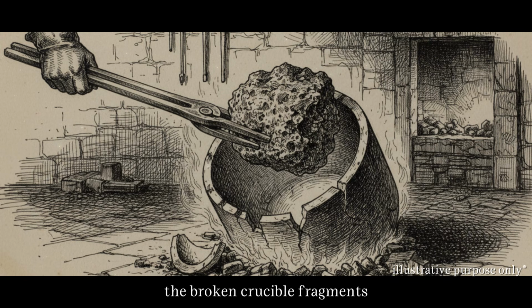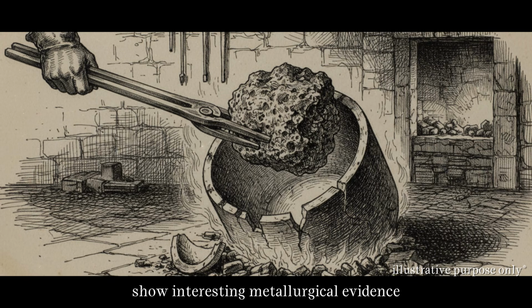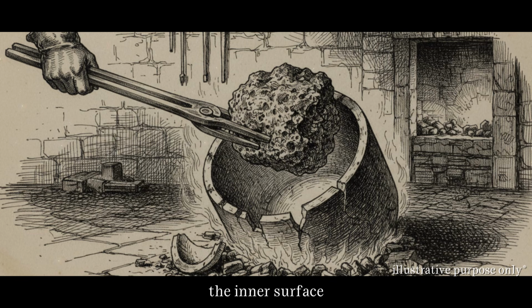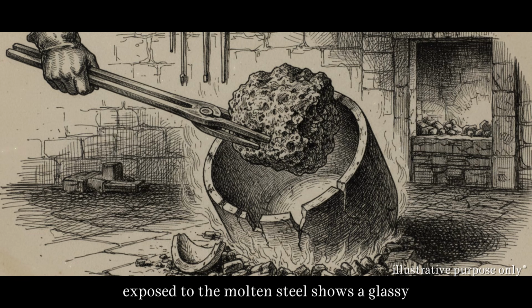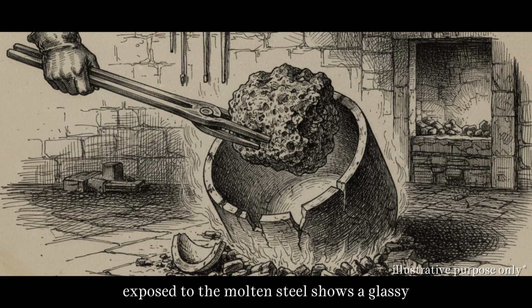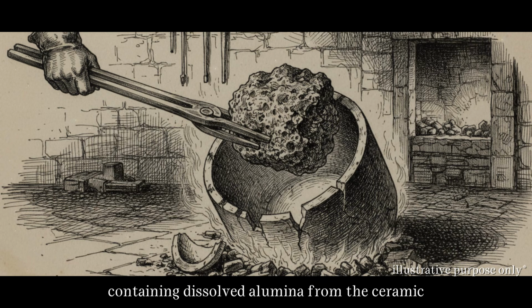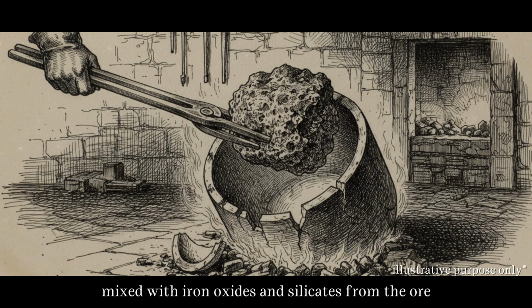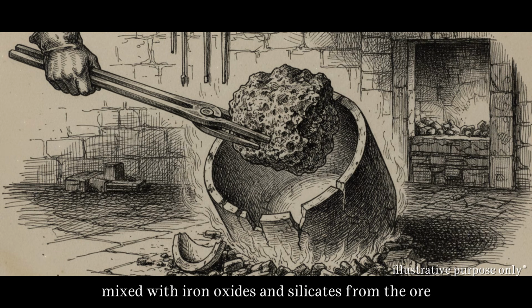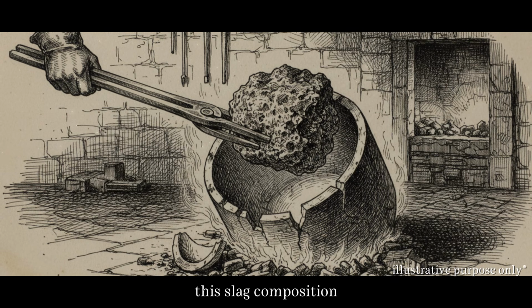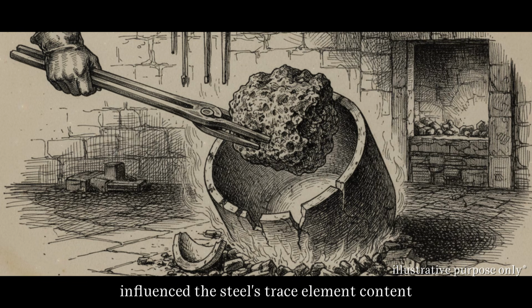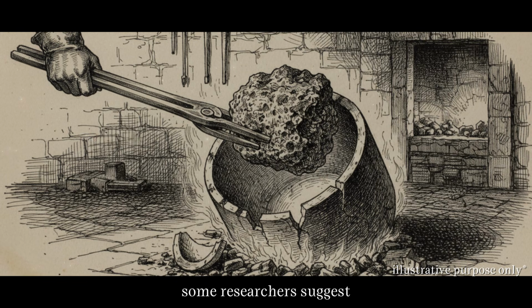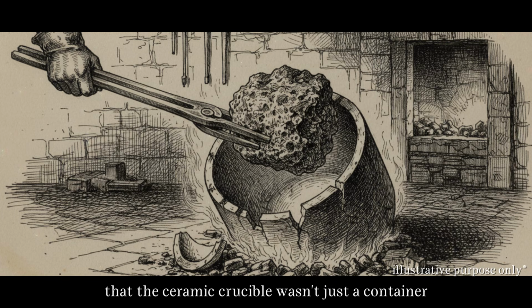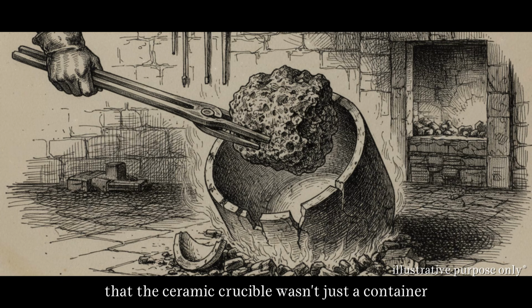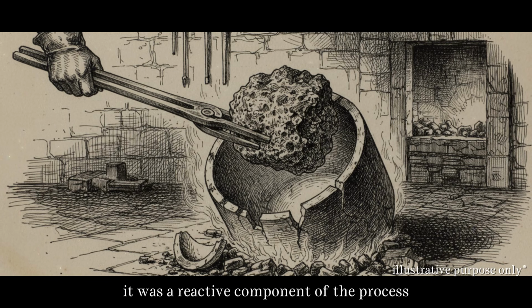The broken crucible fragments show interesting metallurgical evidence. The inner surface exposed to the molten steel shows a glassy slag layer containing dissolved alumina from the ceramic, mixed with iron oxides and silicates from the ore. This slag composition influenced the steel's trace element content. Some researchers suggest that the ceramic crucible wasn't just a container, it was a reactive component of the process.